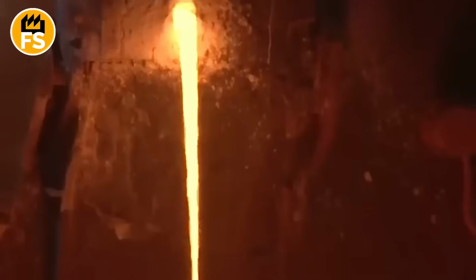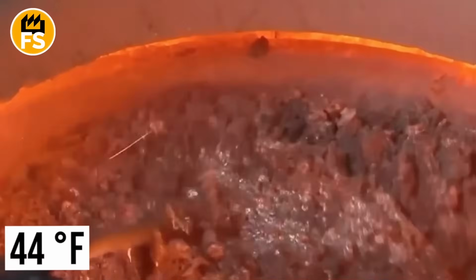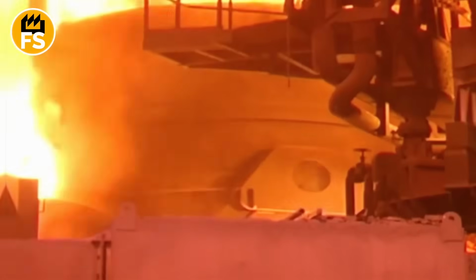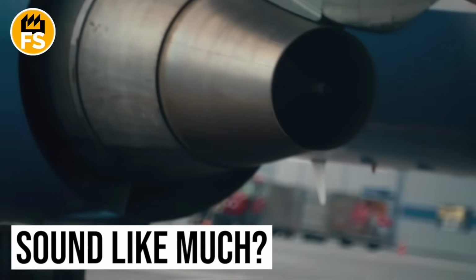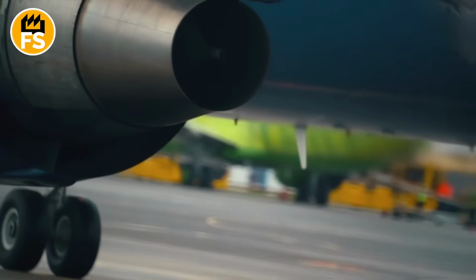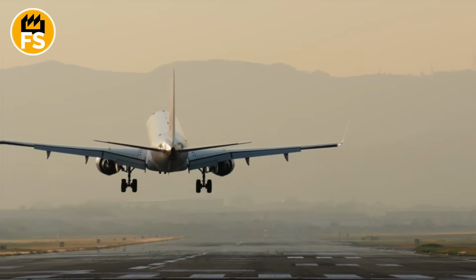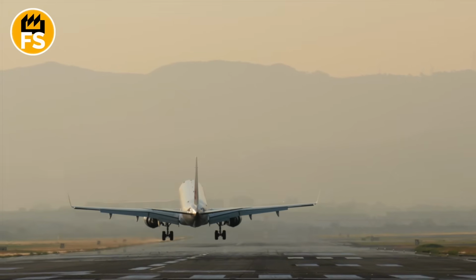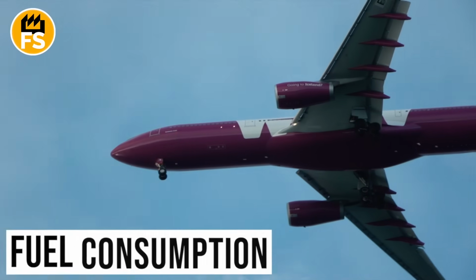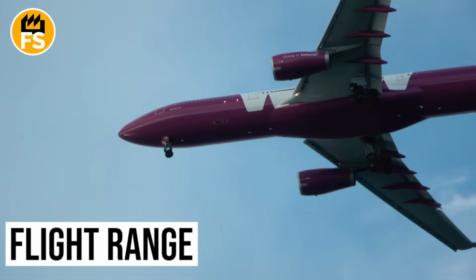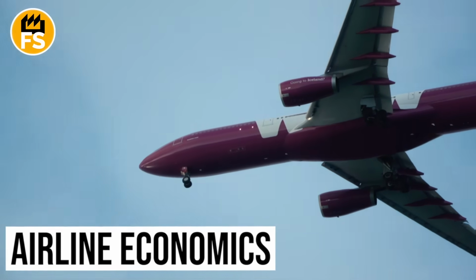Adding just 3% rhenium to a nickel superalloy increases the operating temperature by about 54 degrees Fahrenheit. Doesn't sound like much. But in jet engines, every 18 degrees of additional temperature gives roughly 1% increase in efficiency. And efficiency means fuel consumption, flight range, airline economics.